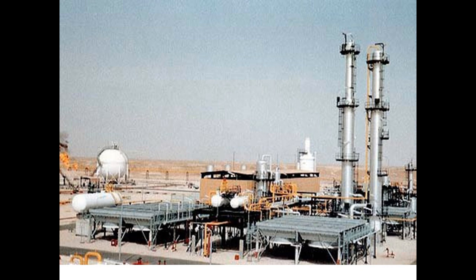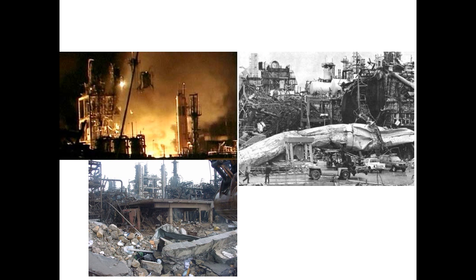Which is actually what did happen to this plant a few days after it was brought back online after some upgrades. We aren't absolutely certain because there's not a huge amount left of it. But what is thought to have happened is that the natural gas contained something which caused the aluminium heat exchangers to stop being robust metal pressure vessels and to turn into a weaker, corroded material with all the mechanical strength of a biscuit — no longer able to hold in the high-pressure gas. Once the aluminium heat exchangers broke, there was a huge stream of natural gas which was easily able to destroy the plant. How this actually happened we'll come back to later in this lecture.